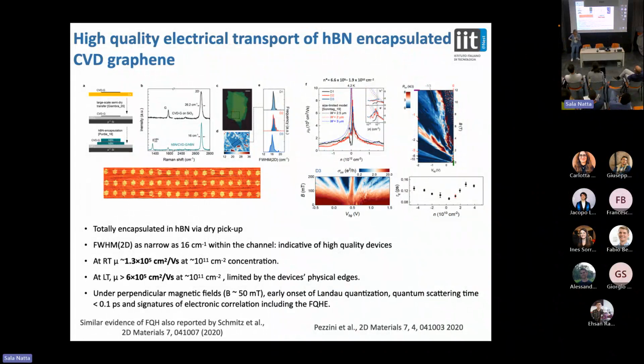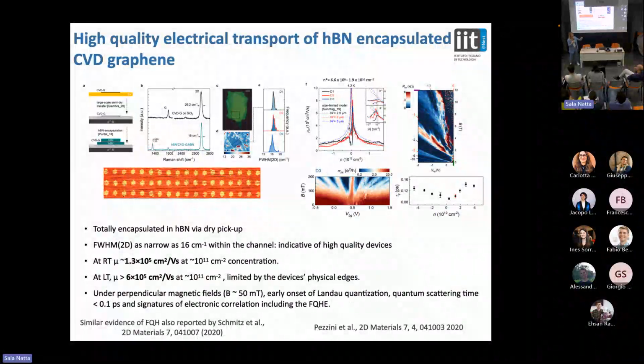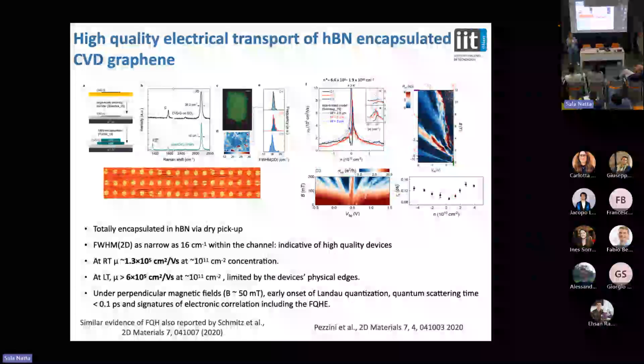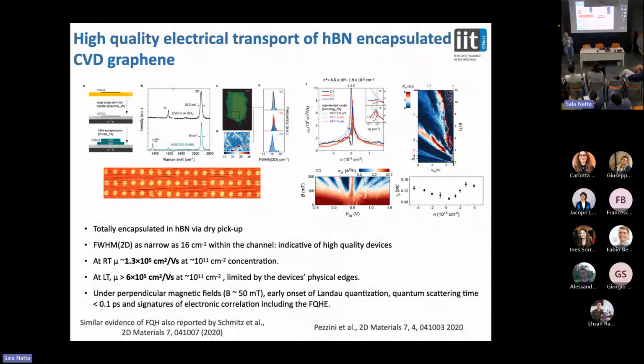Talking again about carrier mobility, how fast electrons and holes travel, we also proved that if you encapsulate graphene, this is not something we proved, it's something known, but we proved the value. If you encapsulate graphene in between two hexagonal boron nitride layers, hexagonal boron nitride is the white brother of graphene. Graphene is the black brother, it's black actually, graphite, right? And boron nitride is white. And it's exactly like graphene.